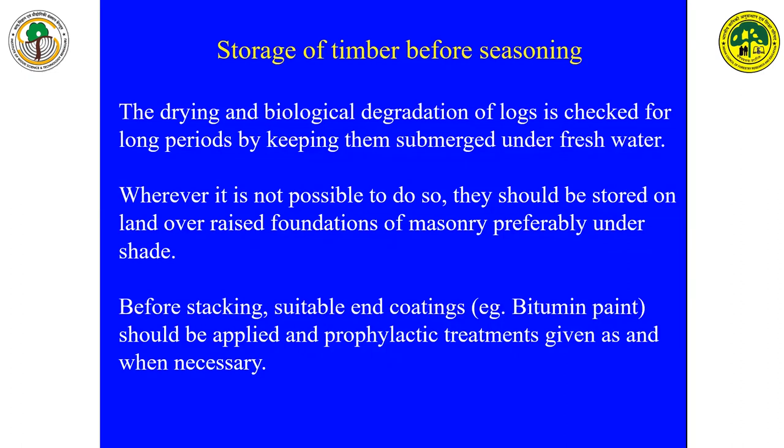Another thing, for prophylactic treatment, we should make a 2 to 3% solution of boric acid and borax in water, and spray it frequently, say every 3 months, so that borer attack or fungus attack won't be there. So this is the method of storing.